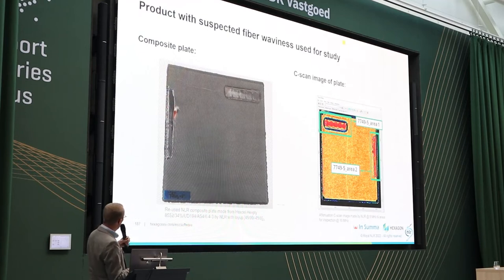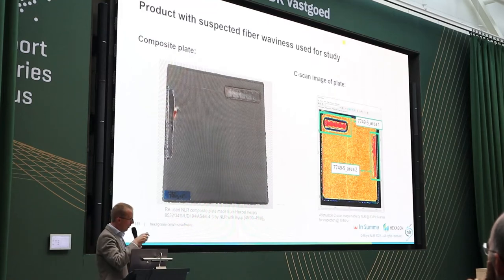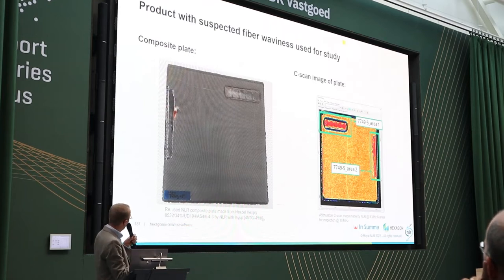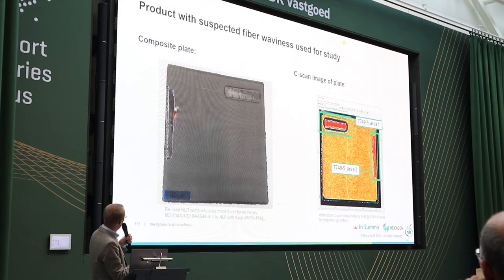So in the end, I found the plate you see on the left. A composite plate was used for another project, also to cut coupons from, but it was also used to test a new silicone rubber material for a vacuum bag for the composite manufacturing process, and that was pressed into the plate. So you see on the left and on the right top where the silicone material was pressed into the plate. We suspected there was out-of-plane fiber waviness, but from the outside you cannot see anything inside.